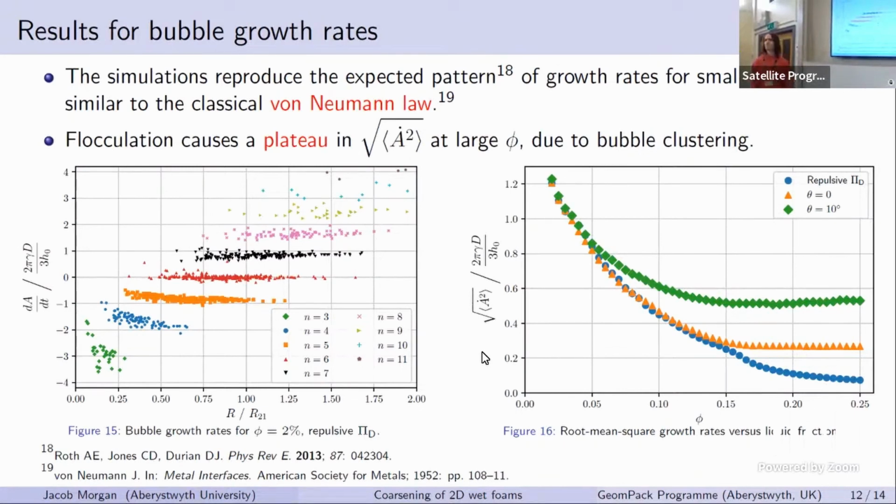Would this be something which is the same from sample to sample? You showed this flocculation, which could be implemented in various ways. So you get a dispersion if you do simple, different random realizations of your simulation. What I find is that depending on the cleanness of that flocculation, the plateau value will differ slightly of the upper curve here. But we have repeated it for several samples for smaller systems, and we find that these sorts of curves are consistent between them.